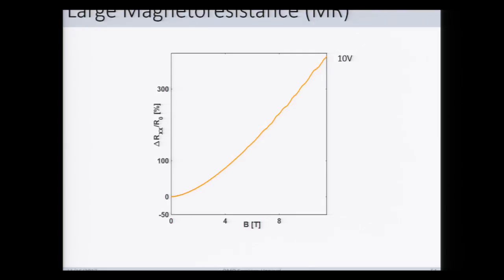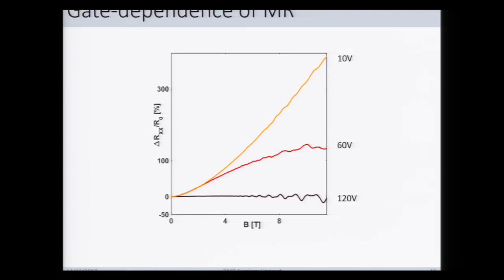And this voltage represents our gate voltage on our field effect device. And the main point of having this is that unlike bulk samples, in 2D you can use the field effect to change the density of the sample and see how physics evolves as you do that. And indeed, as we dope the sample by adding electrons and subtracting holes with positive gate voltage, we see the same nonlinear increase at low magnetic fields, saturating to a constant at large field. And then at the highest gate voltage we can apply, we see no magnetoresistance whatsoever.